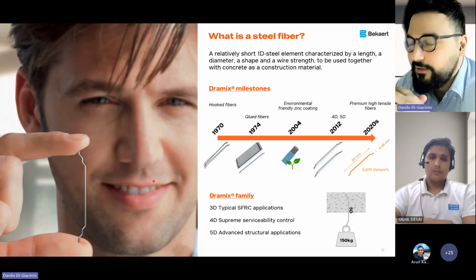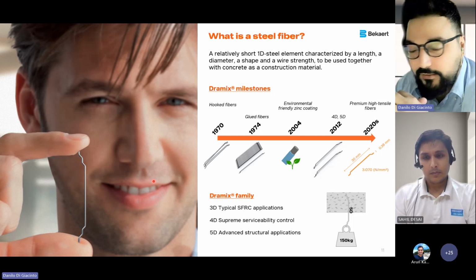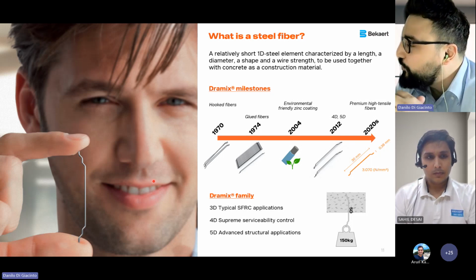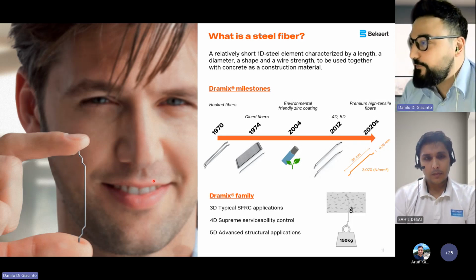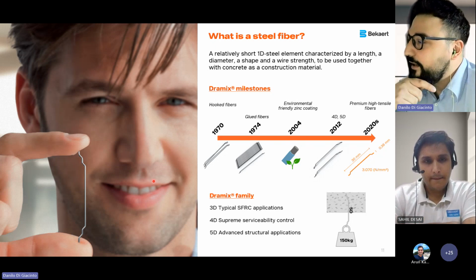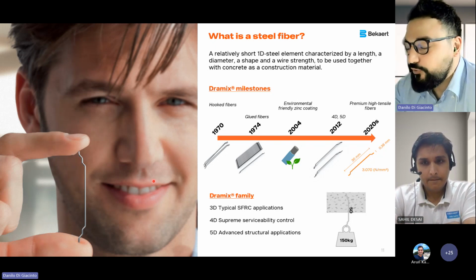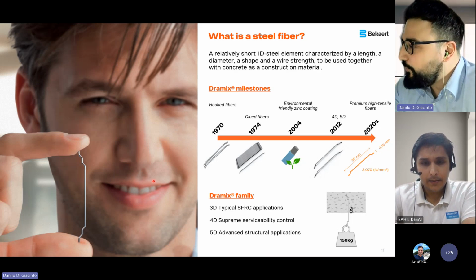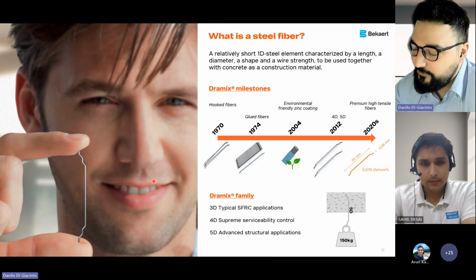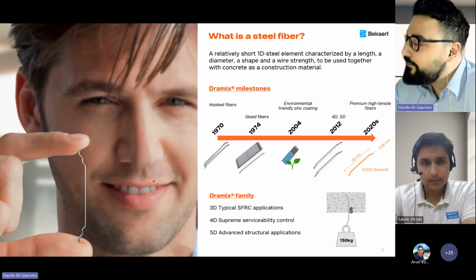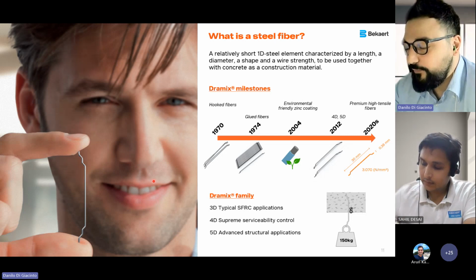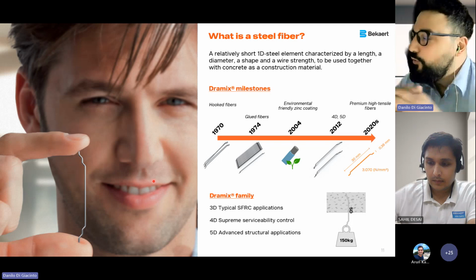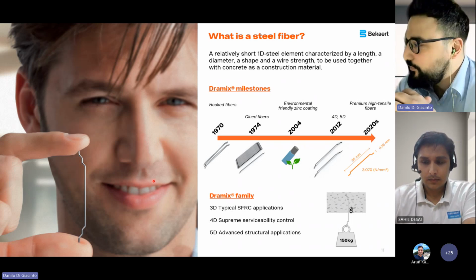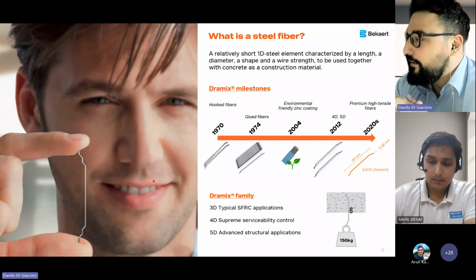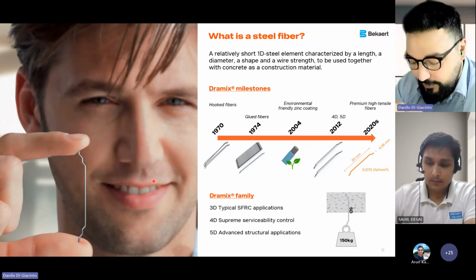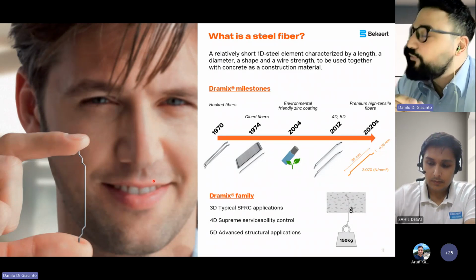Few milestones of Dramix, since Dramix is one of the most copied construction products all over the world. It has been invented as a hooked fiber, so improved anchoring mechanism, in 1970. In 1974, to avoid bonding of steel fibers, we invented the concept of glued fibers. So the fibers are packed in bundles to improve the workability within the concrete mix. And in the glue, we have a special inhibitor for the zinc coated fiber. And indeed, the zinc coating, environmental friendly, very important because we care about sustainability. We introduced it in 2004